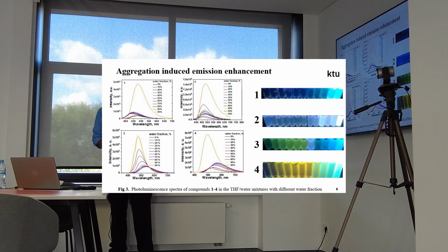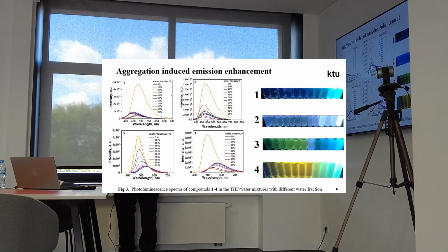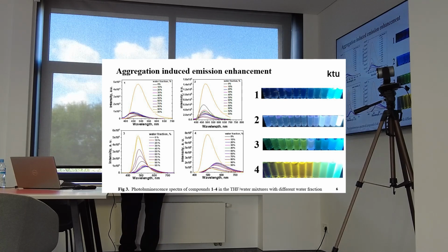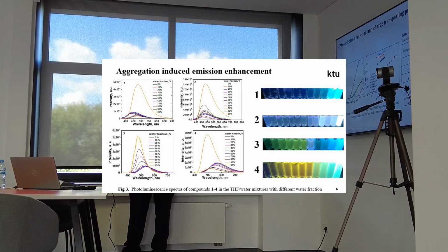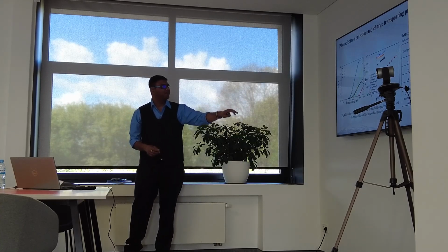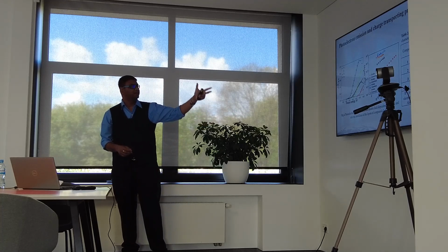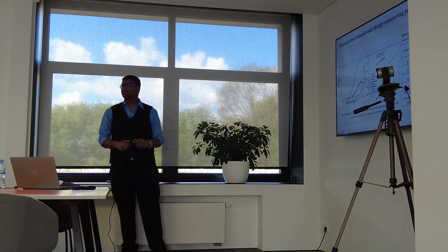In order to investigate further, we studied aggregation induced emission enhancement by dispersing the synthesized compounds in THF and water fractions, with water ranging from 0 to 95%, and for compound 3 at 60%, and for compounds 1, 2 and 4 at 90%, we observed an increased intensity of emission due to the formation of aggregates, which in turn restricts intramolecular rotations. Photoelectron emission and charge transporting properties of the materials were studied, and it is revealed that for compounds 1 to 4, the ionization potentials are in the range of 5.8 to 6.4 electron volts, and time of flight measurements revealed that compound 1 displayed highest electron and hole mobilities at 10 power minus 3 square centimeters per volt seconds.